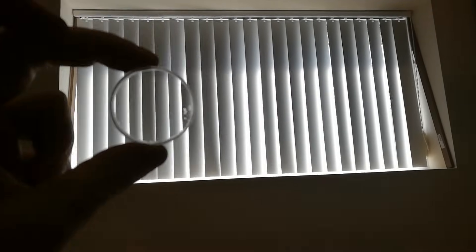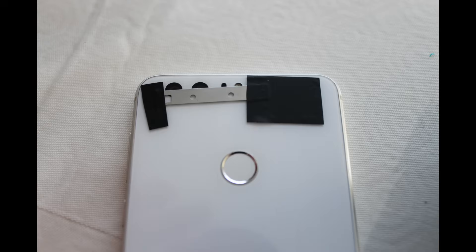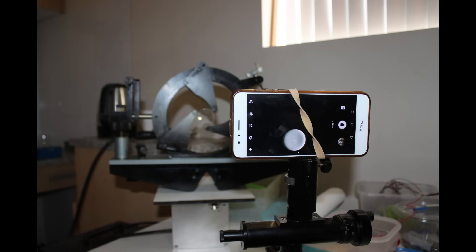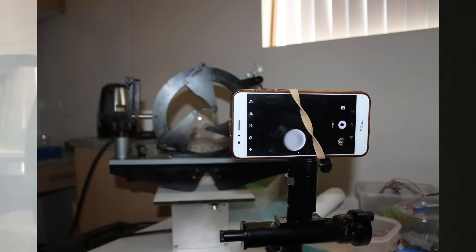It is possible to make a very simple Foucault tester from just a smartphone and a razor blade, by placing the razor blade halfway over both the LED and the lens. When the lens and the LED are positioned near the center of the concave spherical surface, a Foucault image shows up on the smartphone screen, allowing for a quick evaluation of the surface.